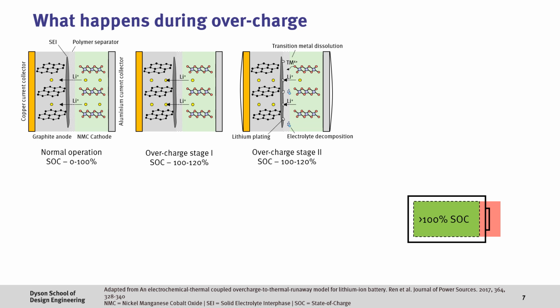Furthermore, as the voltage of the cathode gets higher, this leads to the decomposition of the liquid electrolyte, forming gases which cause the cell to bulge, and also the cathode becomes increasingly unstable, leading to transition metal dissolution.